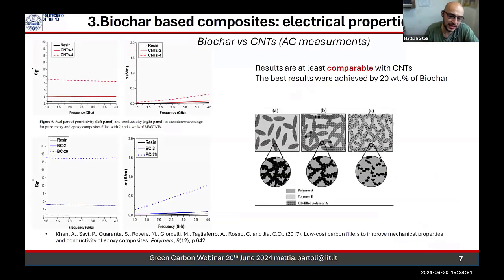Our very first study in this field was a benchmark study. We took a commercial biochar, one of the ones that Prof. Mašek is producing in Edinburgh, and we compared it with carbon nanotubes. And we saw that we can obtain something that is quite similar. Of course, we use a lot of biochar for doing the same thing. But if you keep in mind that properties should be balanced with carbon sequestration and the overall impact of this process, it is something that can be interesting.